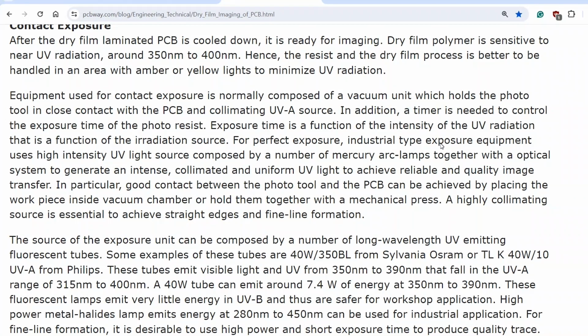For perfect exposure, industrial type exposure equipment uses a high intensity UV light source composed of a number of mercury arc lamps together with an optical system to generate an intense, collimated and uniform UV light to achieve reliable and quality image transfer. What is important here? Use a high intensity UV light source. I saw on YouTube many DIYers use a really weak source, and exposure times are up to 10 minutes. Not good. It's the same for outdoor exposure. You can do it, but it's better that you have something between 5 to 30 seconds of exposure. That means a high intensity UV light source.